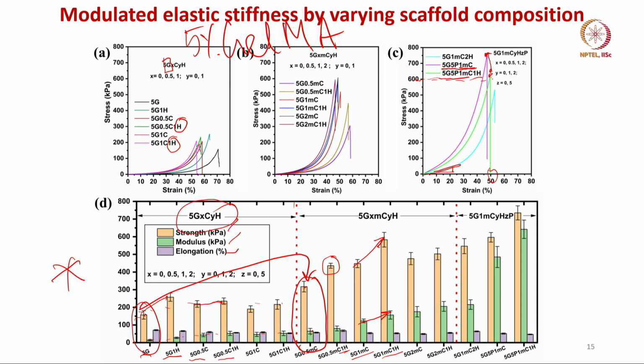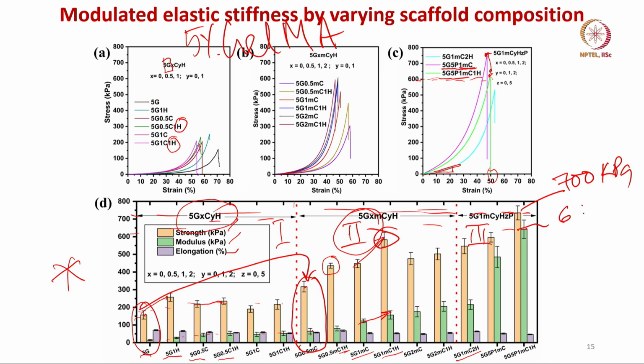Now, suppose this is group 1, this is group 2 and this is group 3. In group 2 scaffolds you can certainly appreciate that the strength improvement is quite significant compared to the group 1 scaffolds. In the group 3 scaffolds, we have 5% GelMA, 1% modified carboxymethyl cellulose and 2% hydroxyapatite. When 2% hydroxyapatite is added, you can essentially achieve a strength value of almost 700 kilopascal and a modulus value close to 650 kilopascal. So, this is sigma c, the compressive strength, and this is E, the compression elastic modulus.